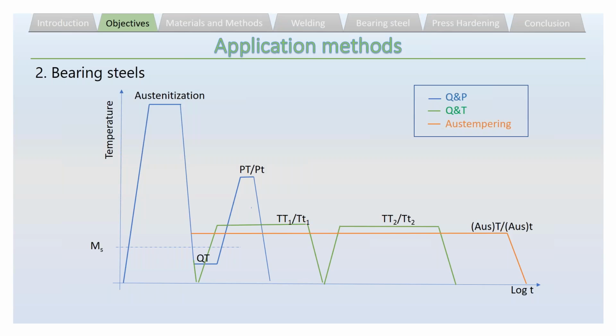The second application was bearing steels. You may know that bearing steels are usually high carbon content steels. They should be hard and usually martensitic. But we normally don't like to have high carbon martensite because, as you know, it's as brittle as glass. The ductility of such structures is like 1%, for example in the bearing steel 100Cr6. What they usually do for bearing steels in industry is that they quench first and then temper 1 or 2 times for 1 to 2 hours.